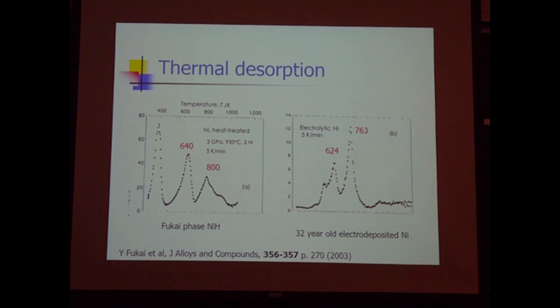So this argues for thermal desorption being a diagnostic for vacancies. So if you like, we have a tool now. You can imagine doing Schwack co-deposition, or doing co-deposition under Pamela's protocol, say for example on copper, and then doing thermal desorption afterwards. Now if it's true that there are no vacancies being created because the current density is not high enough and the surface loading is not high enough, then you should see the palladium analog of this peak and not the palladium analog of either of these peaks.